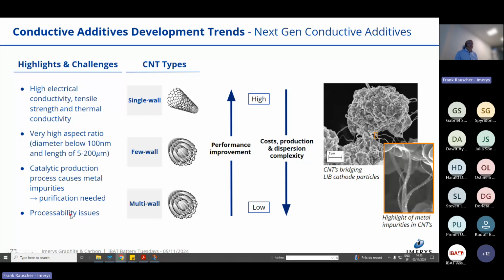So you always need to work with slurries. You provide dispersions to the customer so that they are not forced to deal with dispersion issues that come with the CNTs themselves. So you need to provide them something they can use right away. The other point that's a bit of a challenge for CNTs: CNTs are made by using a metal oxide as a catalyst. So in the product, you have metal oxide fragments coming from the catalyst. Depending on where the CNTs are being used, it may not be acceptable for customers to live with those impurities. So that requires then an acid washing. And again, this technology today only exists in China, where carbon nanotubes are washed in acid solutions to provide higher purity CNT products to customers.